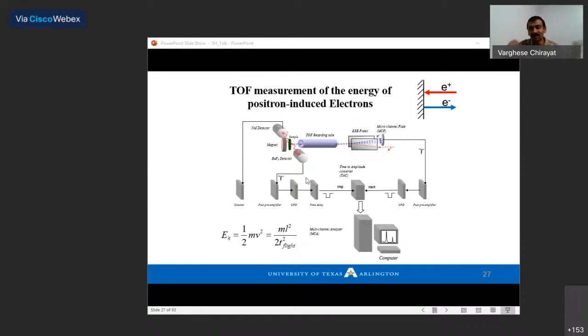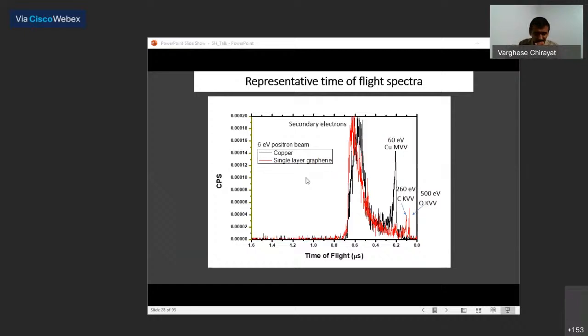This is a representative time of flight spectrum. This is from copper. The black is from copper and the red is from single layer graphene. Let me give a brief outline of the sample here. The single layer graphene is grown on a copper substrate. It's just one layer of graphene on copper. We took the spectrum, and then we cleaned the graphene out. That is, we sputtered it out. We kind of rubbed the graphene away, and we get clean copper.